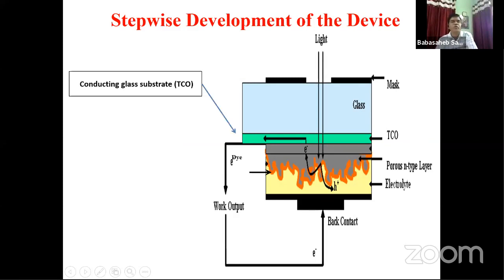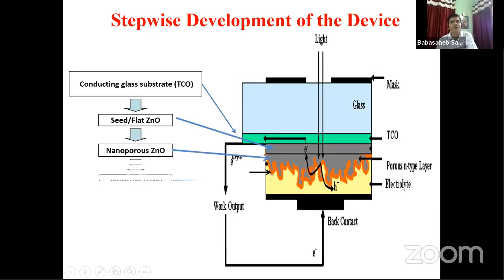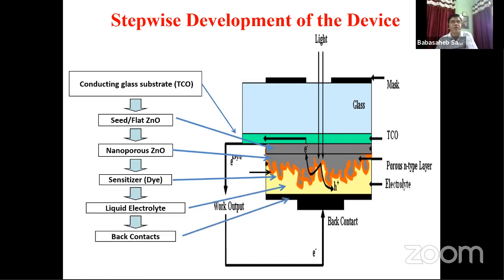These are the stepwise development. That is the TCO layer, which can be FTO or ITO. Here I am considering zinc oxide. So I call it a seeded or flat zinc oxide, then nanoporous zinc oxide, then sensitizer dye, and then liquid electrolyte and back contact, and finally device testing.